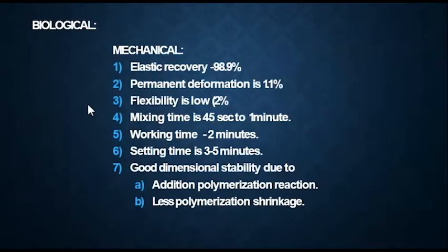So you should remember, elastic recovery is best in addition silicone impression material, and highest wear strength and highest flexibility is in polysulfide. Now coming to polyether, it has elastic recovery of 98.9%, has a permanent deformation of 1.1%, and flexibility is less compared to addition silicone. And mixing time is 45 seconds to 1 minute, working time is 2 minutes, and setting time is still low, 3 to 5 minutes.